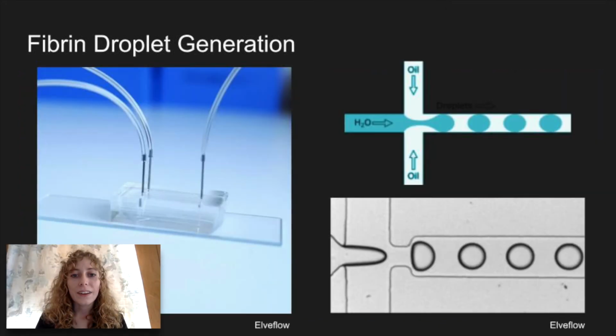To begin, the device is customized to produce droplets of a specific size and composition. In our lab, we commonly use droplet generating devices that produce droplets that are 50 microns in diameter. To begin, the desired solutions are prepared. In this case, a solution of fibrin and oil are needed. The fibrin solution is placed in a vial and pumped into the microfluidic device via inlets.